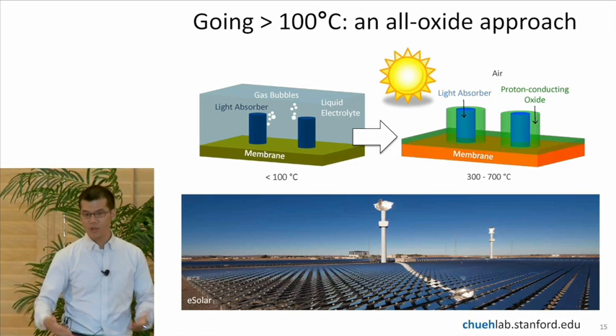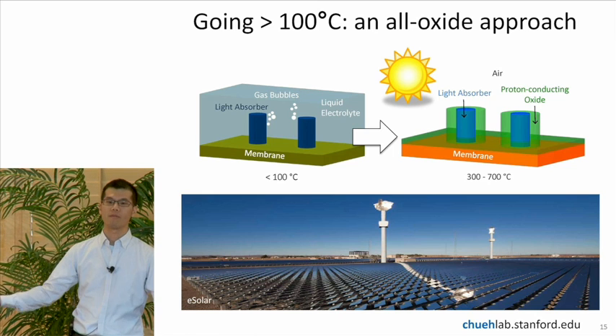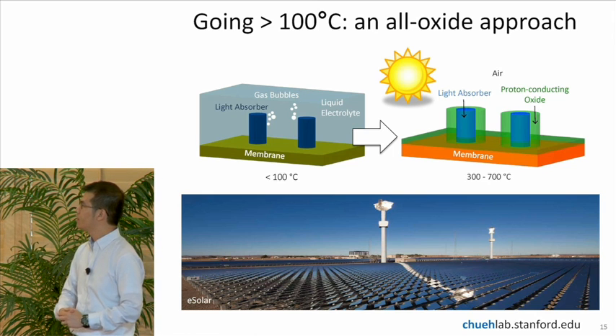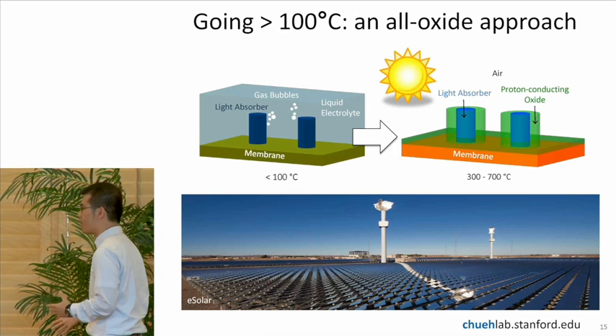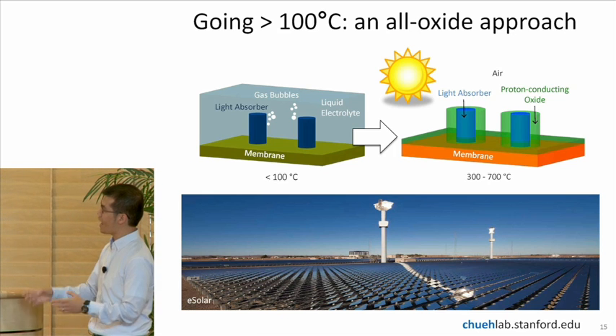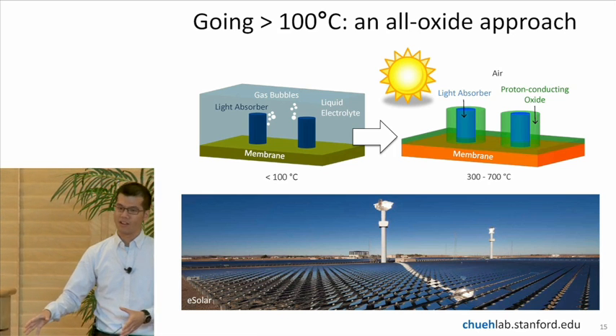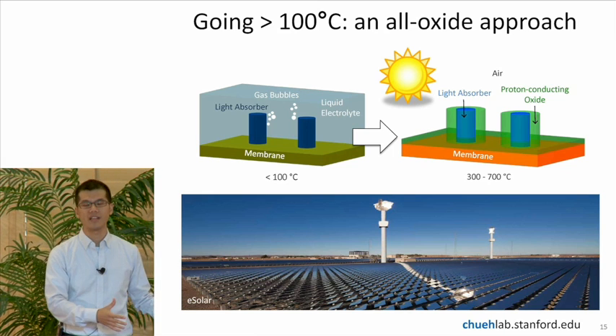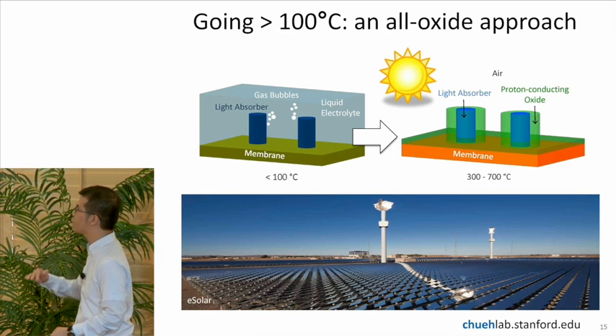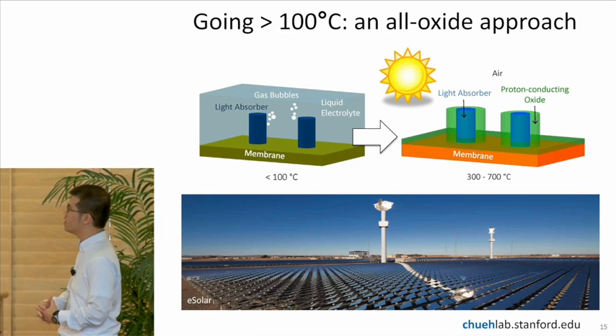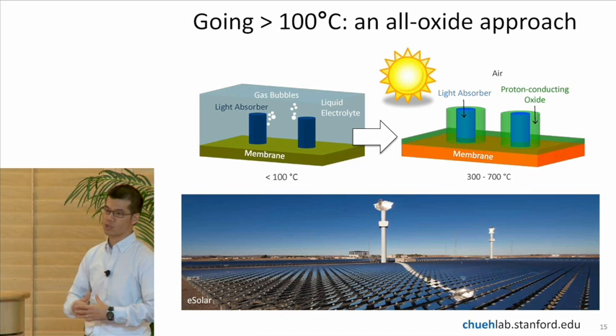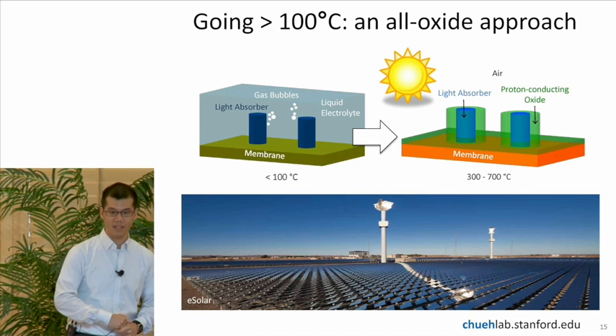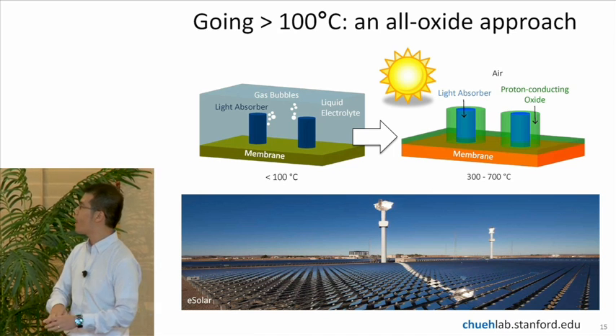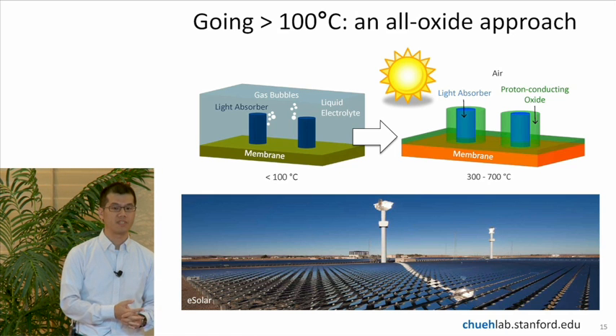All is great. We can go up to about 100 degrees C, but then water boils, then we're out of luck. So actually, the main thrust of our GCEP work is to look at how to take the liquid cell up into a solid state cell in which the temperature can go far beyond 100 degrees Celsius. So we essentially take the liquid electrolyte and replace it with a solid electrolyte. That can go much higher in temperature. These are typically ceramic materials.